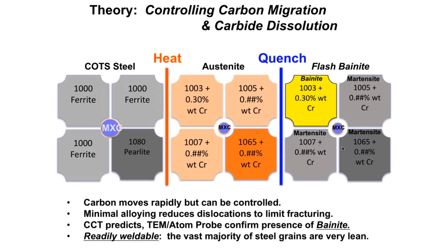As soon as that steel solidifies, in a crude sense, you could call it AISI 1000 plain carbon ferrite, as represented by three of the gray boxes on the left-hand side. It could also be part 1080 pearlite, and then the M7C3 represents the chromium carbide. So again, a little bit of a crude representation, but when you buy 4130, you're actually buying ferrite, pearlite, and carbides. In a typical heat treating operation, your goal would be to heat for many seconds or minutes to try and dissolve the carbides, level the carbon, and fully homogenize the austenite. And that's how steel heat treating has been focused for a millennia now.